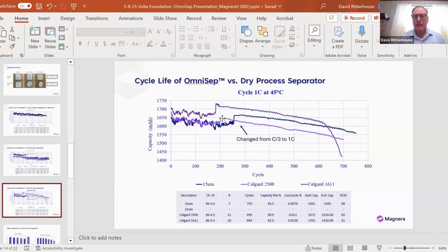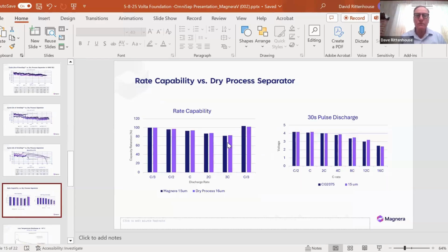And finally, we took other cells and increased the temperature. The objective of this was to get as much data from the cell build as we could. Increased to 45 degrees C. You see this Celgard completely fell off here. This is the OmniSep and the Celgard. So in these three use cases, we were comparable.